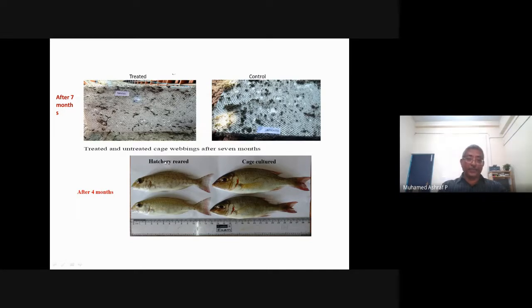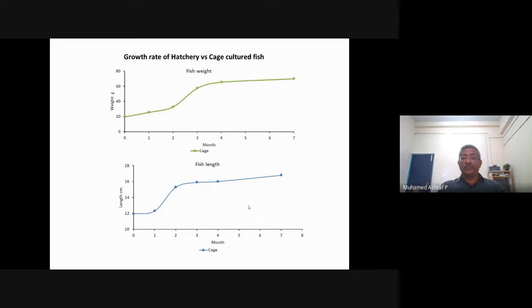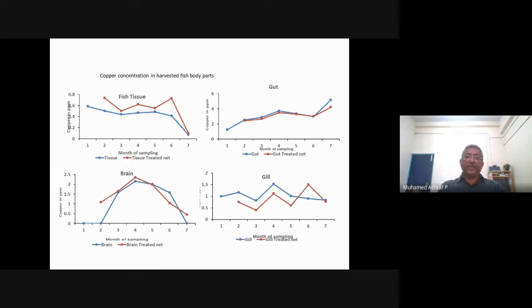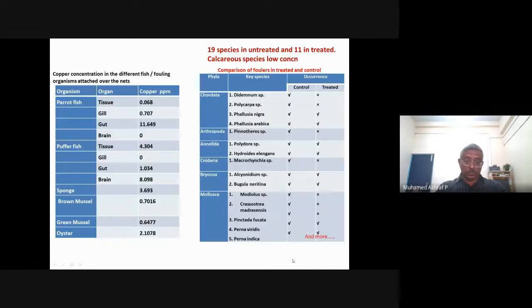This is just a comparison. It is not experimentally right. It is a hatchery reared one and cage cultured fishes. As you can see, the quality was very good. And we analyzed the cage cultured fish based on fish weight and fish length, all was up to the standard reported literatures. And then apart from that, we analyzed the copper concentration in fish tissue, gut and brain. As you can see, there is not much influence from the treated net.